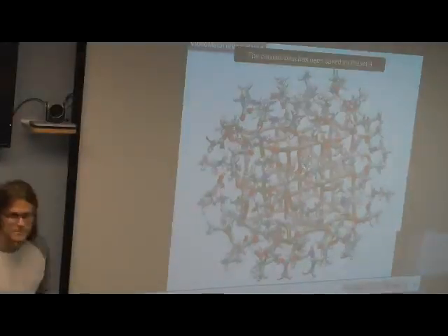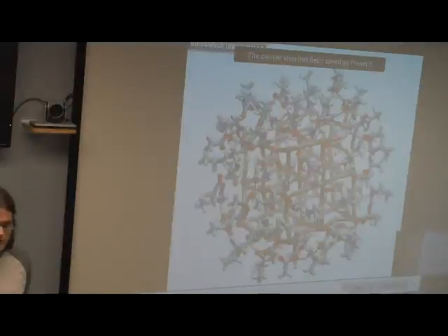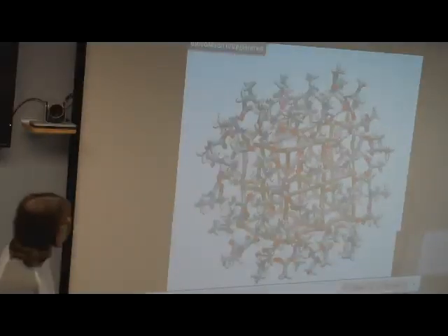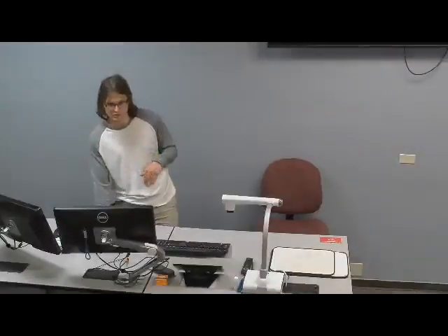What is the temperature here? So this was done at 300K for our model, so it's just molecular dynamics done at 300K. And there's all sorts of vibrations at the surface which pump into the crystal as well. So it's mostly the acids that are bonding to the lead surfaces. And then they introduce bending modes and possibly even some stretching modes, which can act as a heat reservoir, so that if you have an excited electronic state, the electron donates its energy to those vibrations.